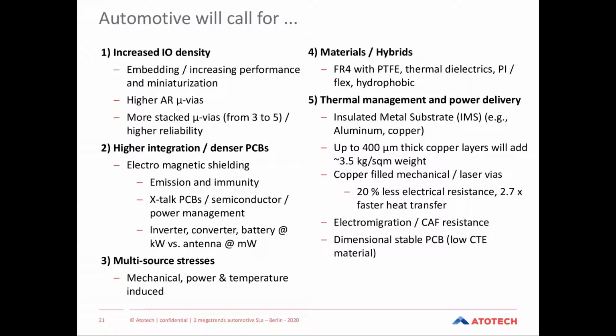At the last bullet point, for thermal management and power delivery, there is a wide field, from insulated metal substrates using lightweight aluminum, for example, or the need for thicker copper layers. But there is a risk that too much copper will add weight, and this could sometimes be too much weight. As an example, just adding a 400 micron thick copper layer within the PCB will add roughly 3.5 kg per square meter of weight, and this will be a lot for automotive.